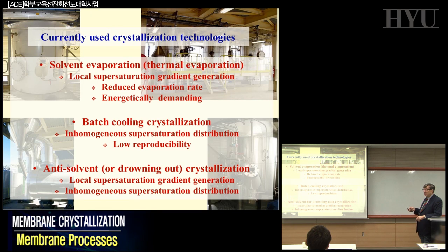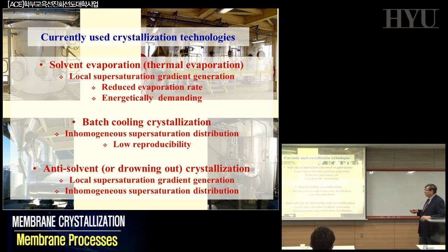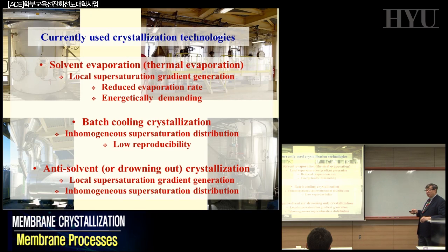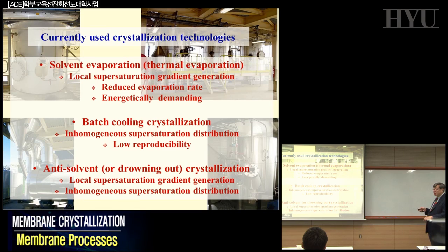crystallization is to create what is called supersaturation, a system in which concentration is overcoming the level in which you can have just the saturation and precipitation. And the local supersaturation gradient generation is one of the key parameters for having a well-controlled crystallization at the end. Because what you have to do in this case, when you're just working in solvent evaporation, is to control the evaporation rate, control the energy necessary to produce this evaporation. These are the parameters. The local supersaturation gradient generation is one very important factor to have at the end high quality in your crystal. We will see what it means, high quality.